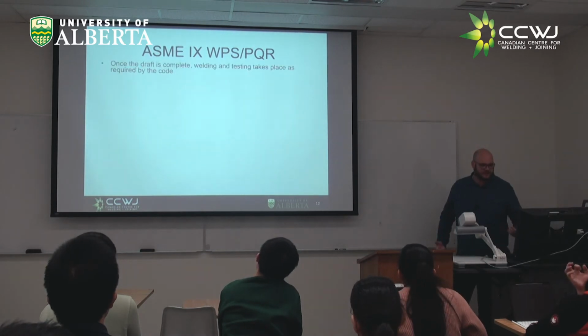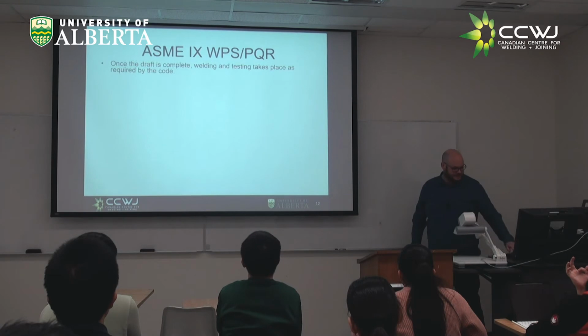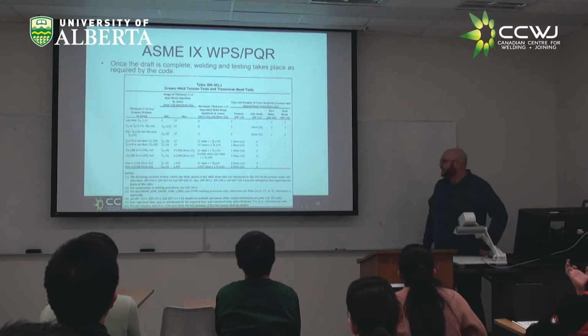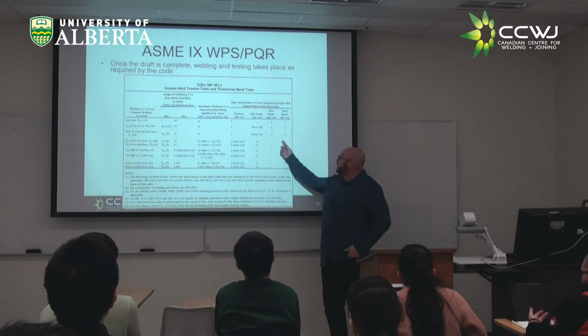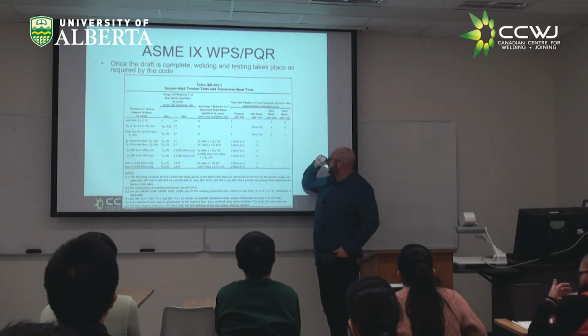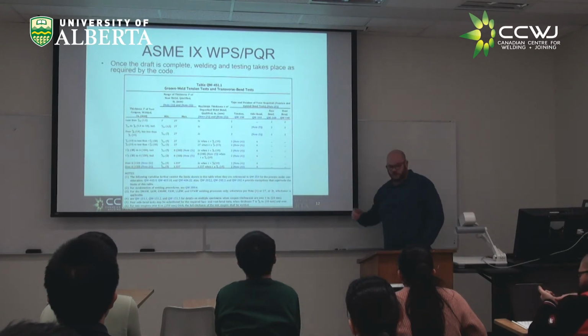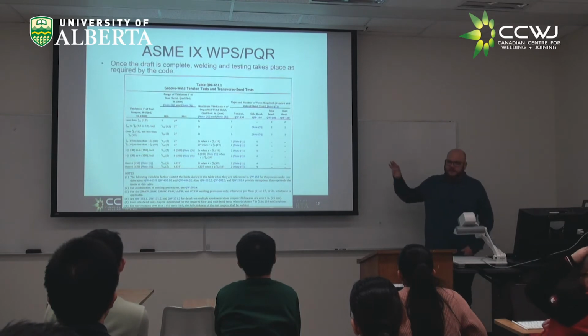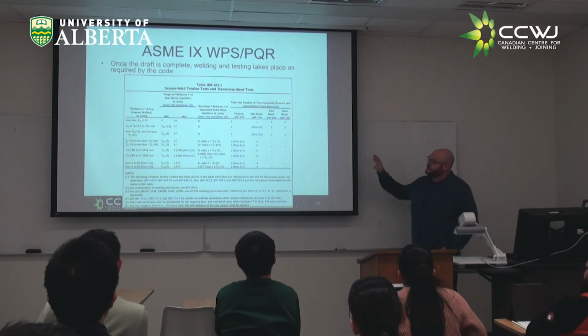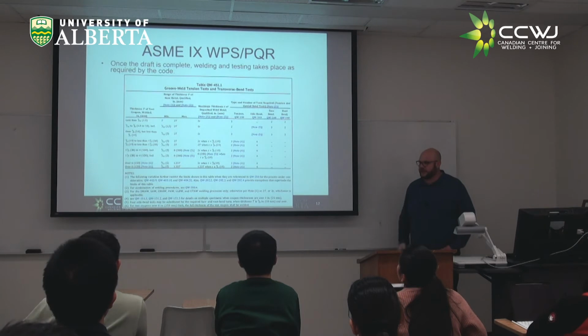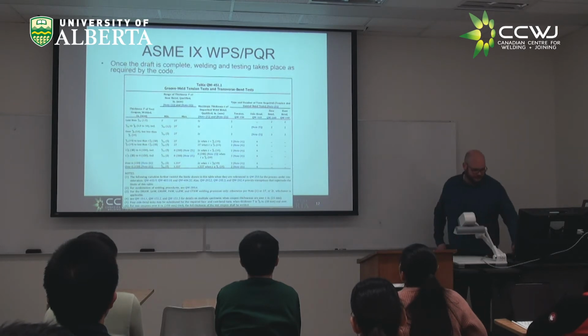So once the draft is complete, welding and testing takes place as required by the code. Again, most of it's delineated for groove welds in 455 or 451. But the other thing I want to draw your attention to is for ASME, and especially ASME 9, the groove weld is king. In the structural world, they pretty much live and die by fillet welds. They rarely do complete joint penetration. Like, it's not used as much. Whereas everything for pressure vessels and piping is usually a groove weld.